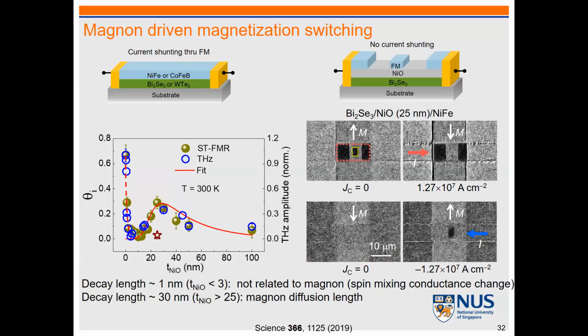So to confirm we can really use this magnon current, we need to isolate our magnet, this ferromagnet. So we etch it out. When we inject our charge current, there will be no current flow inside the ferromagnet. So the only possibility is that current will go through bismuth selenide, because nickel oxide is also an antiferromagnetic insulator. So the charge current is going through, then what happens?